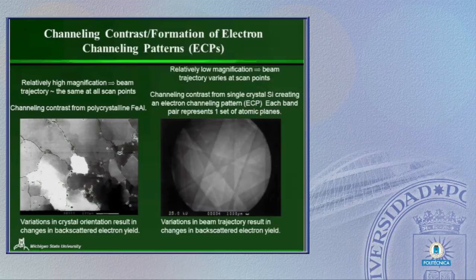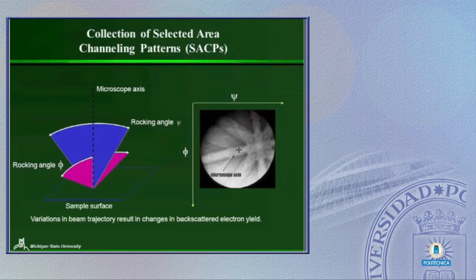And each one of these bands here is going to represent a set of crystallographic planes in the sample. So from this, we could determine the orientation of the sample. But in this format, this is not very useful for us because we're really limited to using this on very large single crystals. But if we rock the beam back and forth through two angles on a point on our sample, and we output the intensity, we can actually then get a pattern that now reflects the crystallography of the sample.